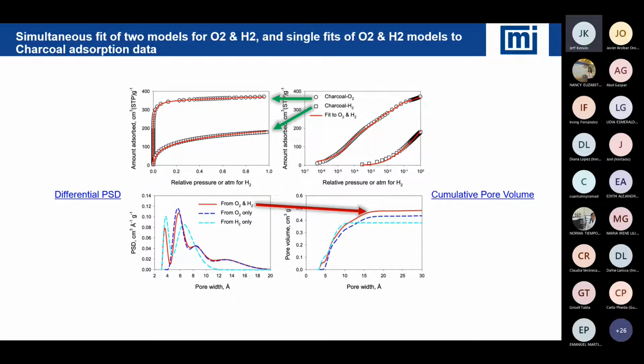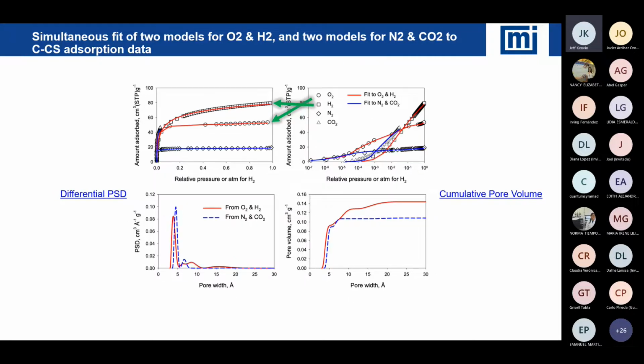So notice with either oxygen or hydrogen, we get very good pore size distributions. Combining them is not unusual. It doesn't create any strange artifacts. But using a combined method, we do see larger pore volume. And that's what the red arrow is indicating, that when we take two together, we're probing more of the pore system because the hydrogen can go to regions of the charcoal that the oxygen cannot get to. And this is one of the classic diffusion problems and some of the issues we have with understanding materials.